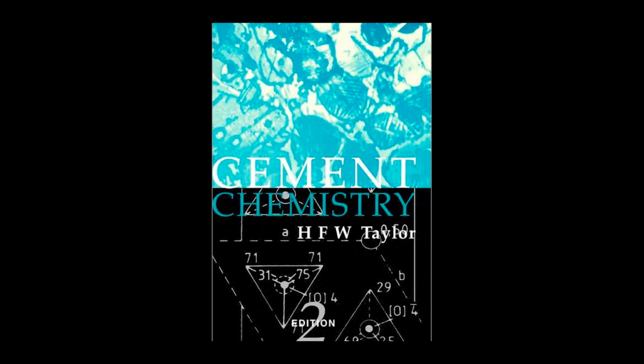Or is it controlled by the duration the material spends at high temperatures, which allows for recrystallization and growth? So even after all these decades of manufacturing, there's still scientific disagreement on how to best achieve that ideal 15 micrometer target. Absolutely. The goal is small crystals for maximum reactivity, but realistically, most production clinkers have average sizes that exceed 15 micrometers. It's a constant compromise between crystal kinetics and industrial throughput.